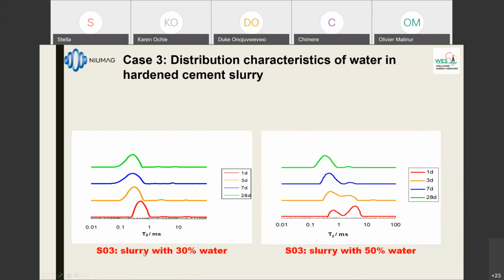That one is interesting. We have two cement slurries. We have a slurry where we put 30% water, and what we see, after 1 day, is one peak inside our T2, while with the 50% water, we have two peaks. Because imagine your cement is water with particles of cement inside and some bubbles. And inside this bubble, you have water. This is the free water inside the bubble, and this is the water with the flocculant.